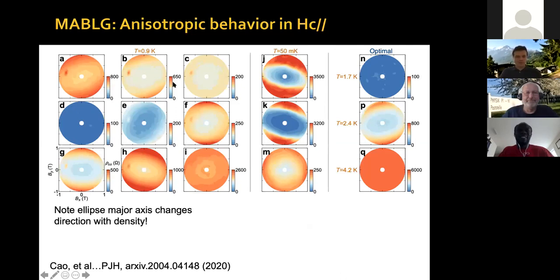So one thing that is nice, okay, because we have a limited magnetic field magnitude for our vector magnet, we can only run up to 1 Tesla in plane. This means that we have to choose sometimes intermediate temperatures in order to determine the orientation of the ellipse. For example, at optimal doping, if you measure even at 0.9 Kelvin, point D is optimal doping, it's always superconducting because the critical field is above 1 Tesla in any direction, okay?